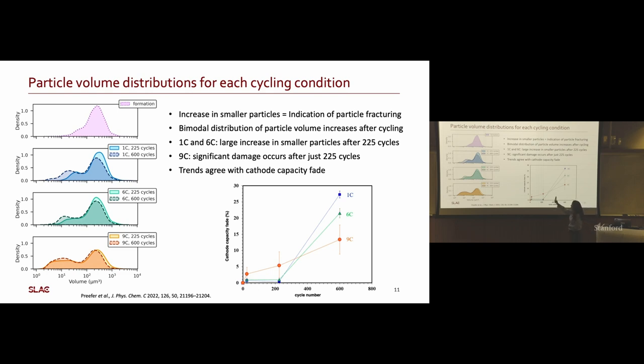And then we can plot the cathode capacity fade, which we get electrochemically, with the cycle number at those different conditions. And we see that the trends do agree. There's more capacity fade, the more smaller particles. So we do think that particle fracturing does contribute to cathode capacity fade. So that's isolating the capacity fade from the anode, which is what we studied before. And so this is just looking at cathode capacity fade. And so why we would get cathode capacity fade when you're fracturing particles is probably that as you're fracturing it, the electrical connection to those fractures is not as good as it was in the whole particle.